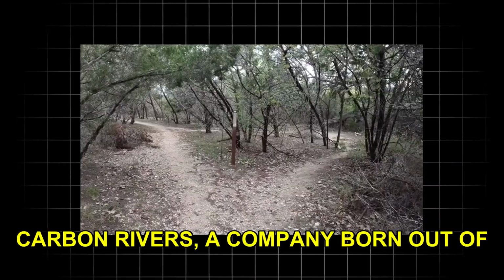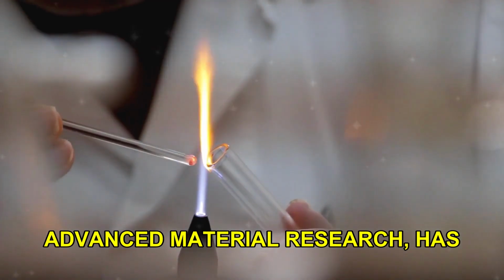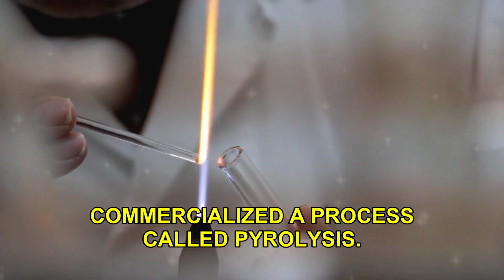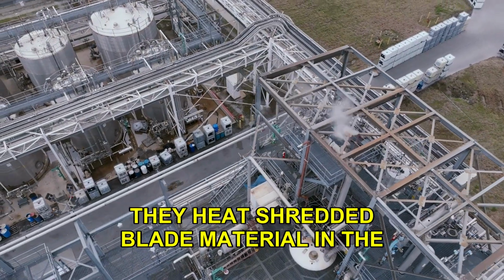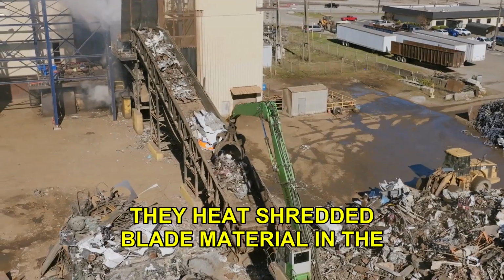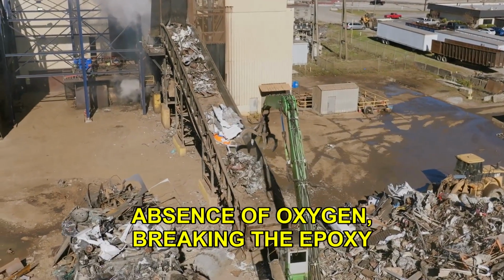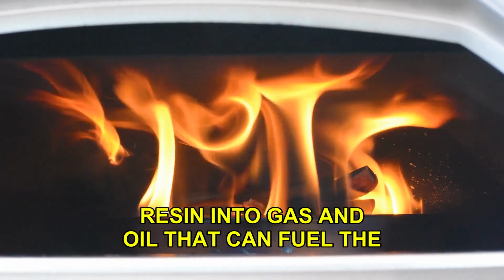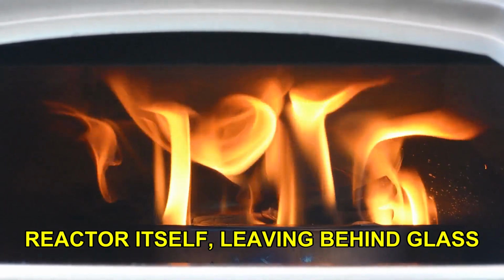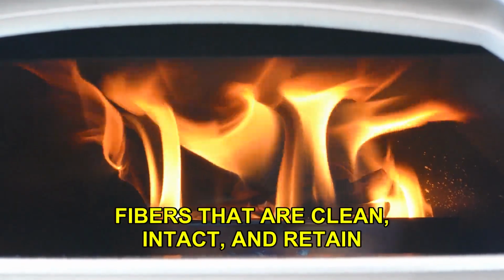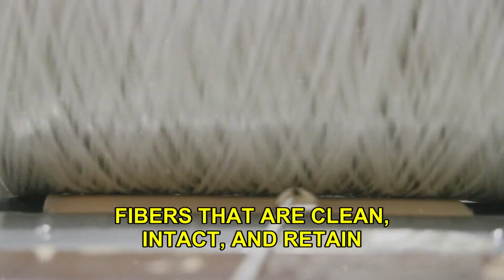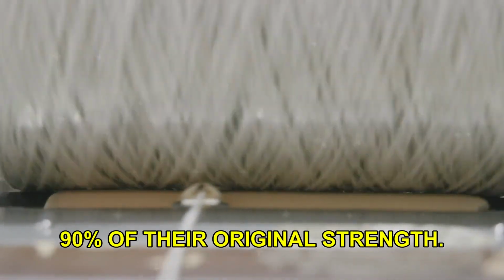Carbon Rivers, a company born out of advanced material research, has commercialized a process called pyrolysis. They heat shredded blade material in the absence of oxygen, breaking the epoxy resin into gas and oil that can fuel the reactor itself, leaving behind glass fibers that are clean, intact, and retain 90% of their original strength.